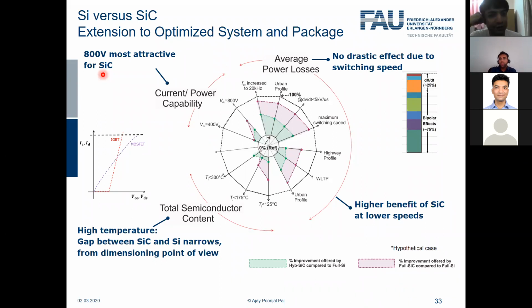Why is this? Because IGBTs are not so optimum at this voltage class. So for an 800 volt system, you would need a 1200 volt IGBT. And in this voltage class, IGBTs are not so attractive because they are bipolar devices. The breakdown voltage has a direct impact on the drift region, meaning that a 1200 volt IGBT would need a thicker drift region compared to a 650 or a 750 volt IGBT. And therefore, you will have more bipolar charges and so on, and you will see more switching losses in the device. So therefore, at 800 volt, silicon carbide becomes more attractive.